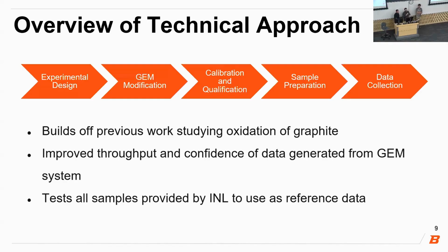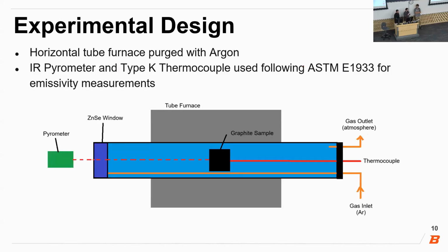So to measure the emissivity of graphite, our team developed this technical approach. It builds off previous work at Boise State and also improves the throughput and data confidence of data generated through our GEM system. This is our basic experimental design. On the right, you can see a flange with a gas inlet, a thermocouple, and gas outlet. In the center is where our graphite sample sits with the thermocouple inserted into it. On the left, you can see a zinc selenide window and pyrometer. Zinc selenide is also a high IR transparency material. The pyrometer and thermocouple work together to measure emissivity using ASTM E1933.